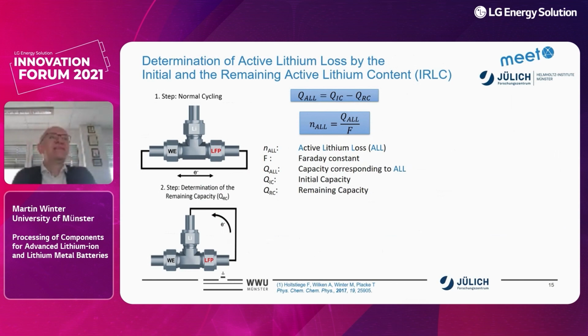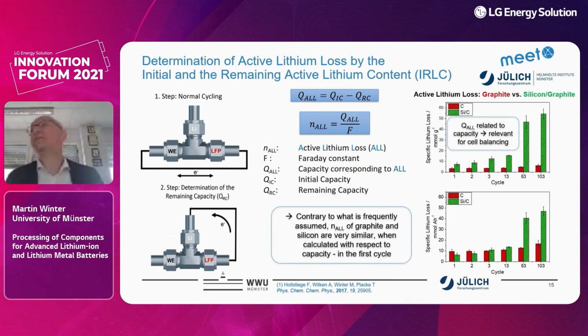And then in the second step, we are disconnecting the cell, and we are connecting the cathode LFP with the lithium reference electrode. And then we are inserting again all the lithium that has been consumed from the LFP during previous cycling with the help of the lithium metal anode. And then we know exactly how much lithium has been lost because we then know the capacity from this experiment. And this gives us very interesting results.